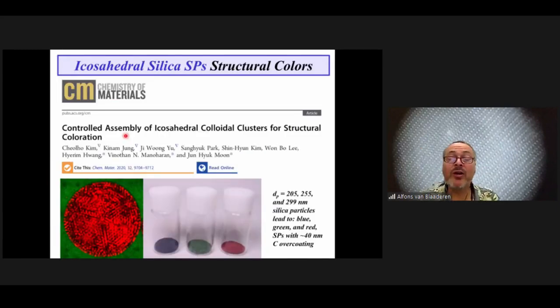What we are working on right now in our group, but the group of Vinny Manoharan was a little bit earlier than us, is that if you do this not with nanoparticles, but with particles of silica, in this case with a diameter of about 300 nanometers, you get beautiful interference colors because of the interference of light. And because of the symmetry of the icosahedral structure that formed inside the superparticle, these colors look the same from all directions. So it's very interesting as a new kind of pigment, because this is not by absorption, but purely by constructive and destructive interference.